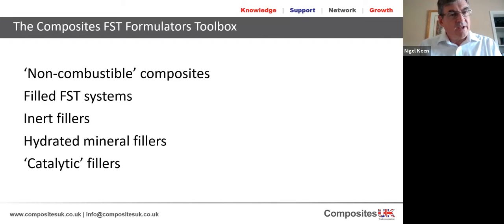When you're talking about fillers, the hydrated mineral fillers are really good as well. Hydrated mineral fillers will be things like aluminium hydrate, releasing water of hydration at certain temperatures. If you've got a process that needs higher processing temperatures, then you might use magnesium hydrate, which doesn't start to decompose until 250 plus centigrade. And other fillers will be multi-purpose, catalytic fillers. Things like the antimony oxides and other metal oxides do more than one thing. They can be inert or non-flammable themselves. They can release non-flammable gases, and they can also act as catalysts to promote some of the other chemistries. They can be useful with bromine, for instance, to increase the effectiveness of some of those other additives.